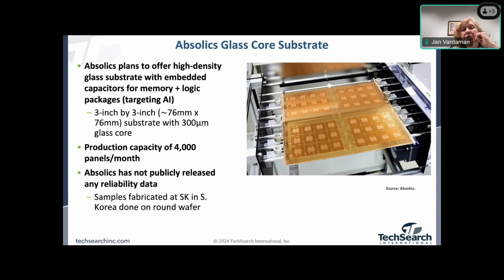Absolics is doing a lot of work on the glass core substrate. They have explained that they're planning to offer these high-density glass substrates with embedded capacitors for memory and logic. At one point, they said they were targeting AI. They said they were targeting a 76 by 76 millimeter substrate with 300 micron glass core. They said they've installed a production capacity of 4,000 panels per month, but they have not released any reliability data.